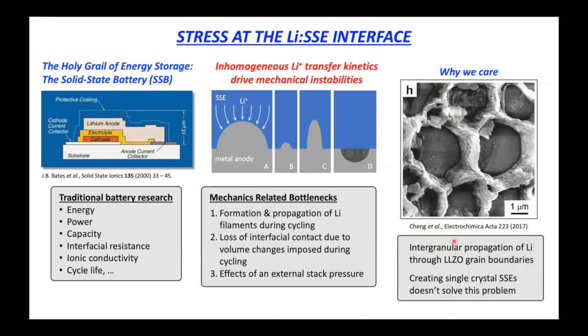Right? So this is one of Jeff Sakamoto's micrographs. I'm sure many of you have seen this on numerous occasions. What I think is particularly fascinating about this, not just this image but the deformation and failure mechanism, is that even when we go to a single crystal version of LLZO, that doesn't just solve the problem, right? The lithium just finds another defect to exploit. It finds another way to penetrate this ceramic separator and cause the cell to short circuit and fail.